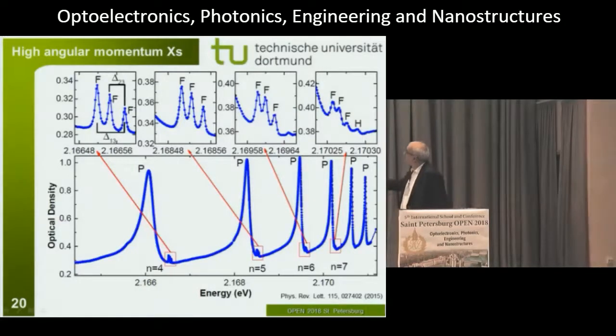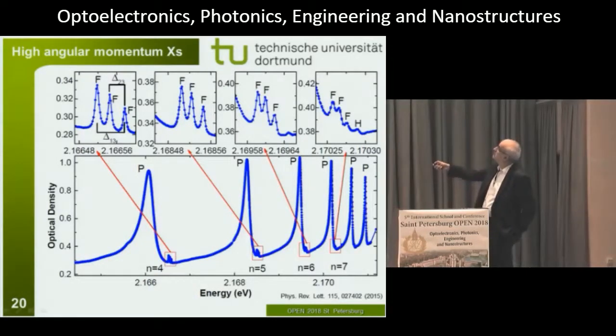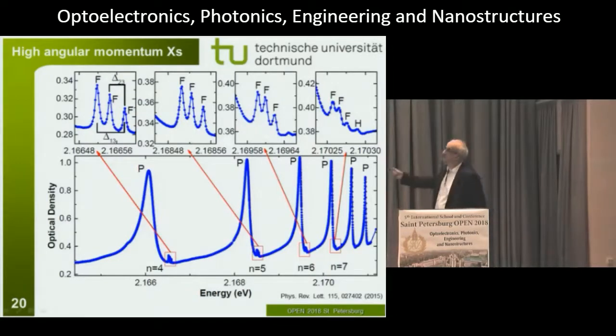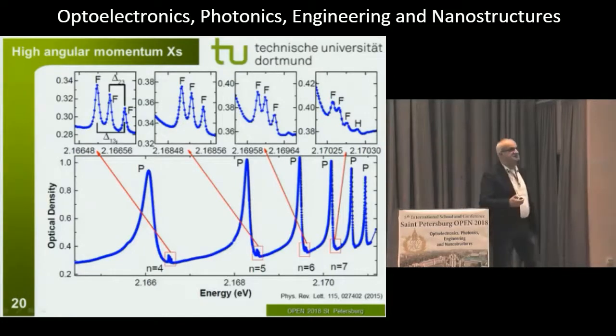And then we found on the high energy side, systematically starting from n equals 4, tiny lines. If you zoom in here, you find that these lines are triplets. The line width is remarkably low. It's on the order of a microelectron volt. And in fact, these are F excitons. So you see that you have a splitting between P and F excitons.